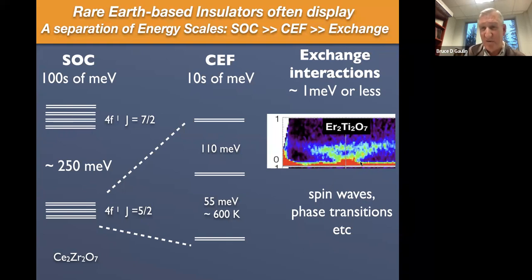And this is a measurement from my own group's much older work on erbium titanate, just showing you spin waves in another rare earth-based pyrochlore. And you can see that the energy scale for these is something less than 1 meV. So condensed matter physics is low energy physics, so it's not surprising that we tend to focus on this.